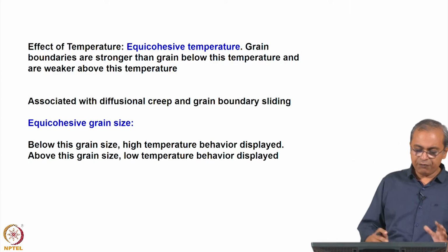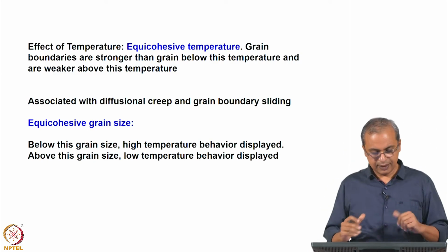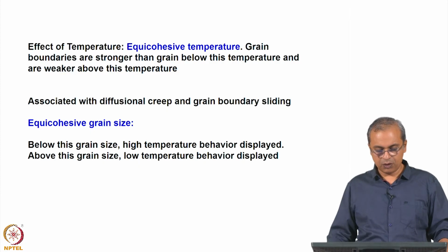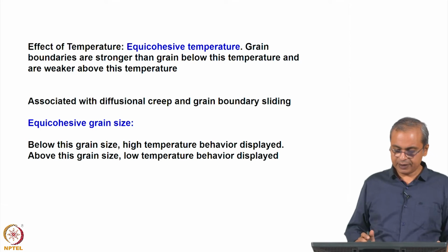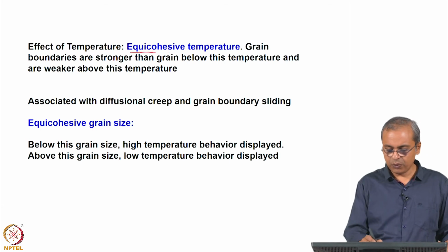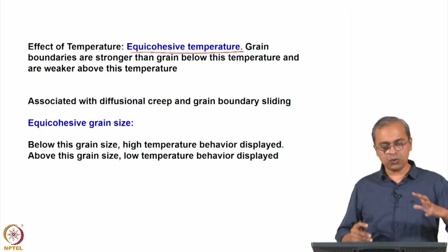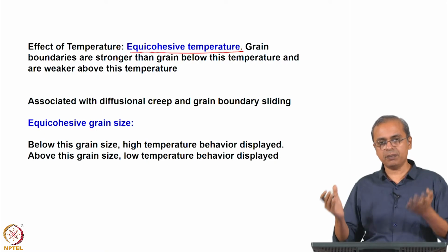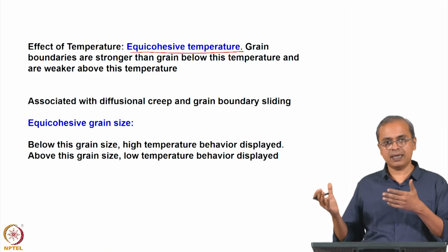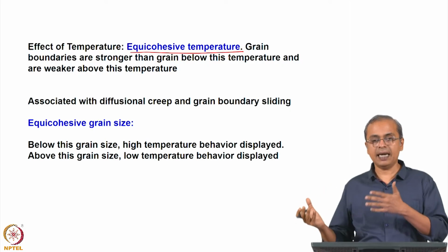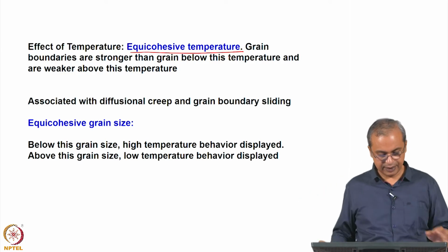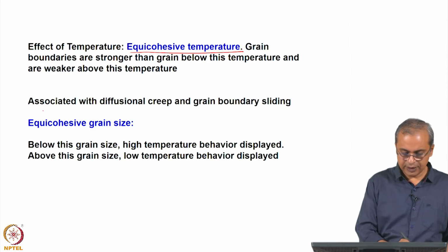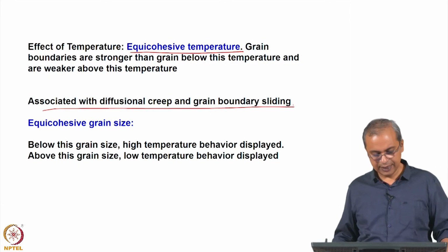So, if you bring these ideas together in some comprehensive manner, we see here that the effect of temperature is captured by the equicohesive temperature. We already saw that. If you raise the temperature, there is a temperature above which the grain boundaries are weaker than the grain, and below this equicohesive temperature the grain boundaries are stronger than the grain. That is an idea that we saw, and it is associated with the diffusional creep and grain boundary sliding.